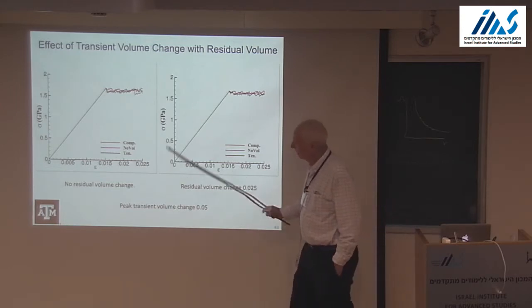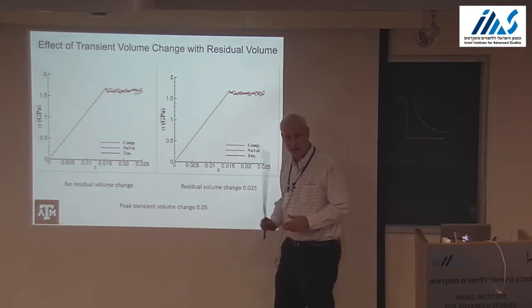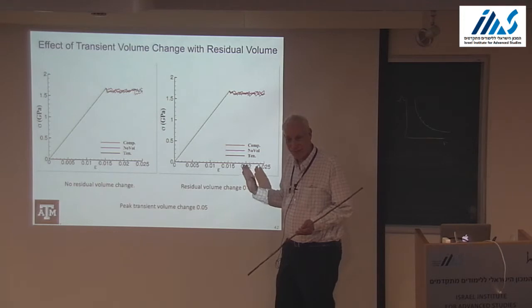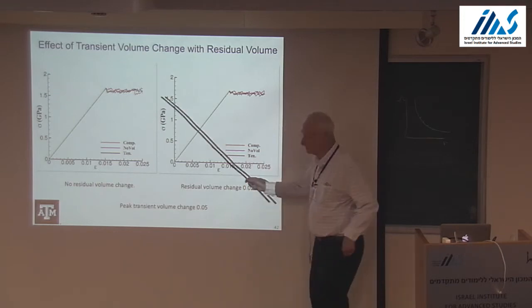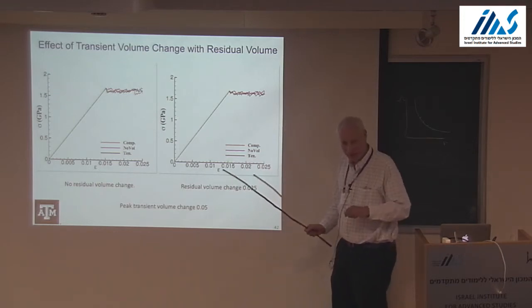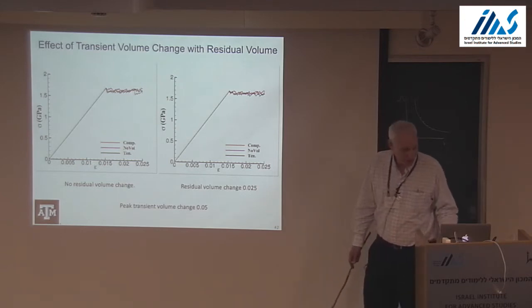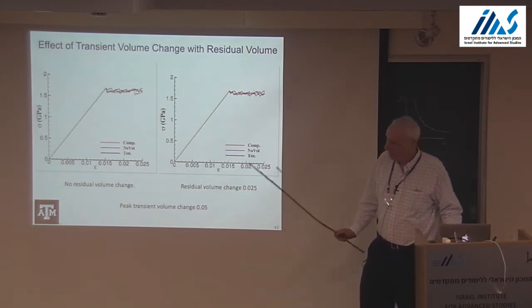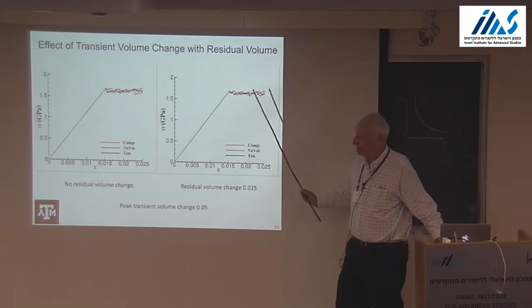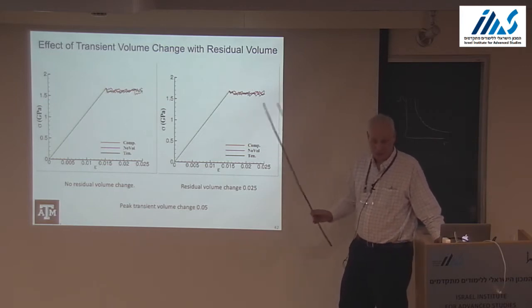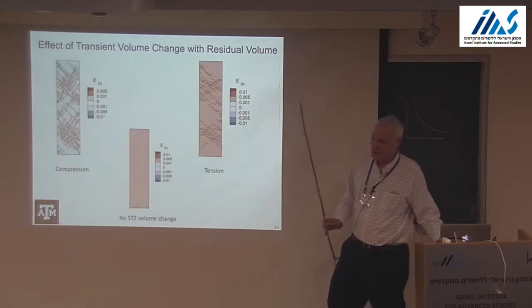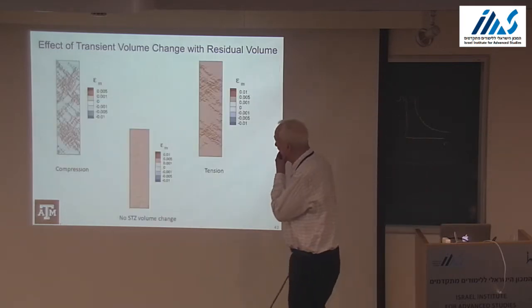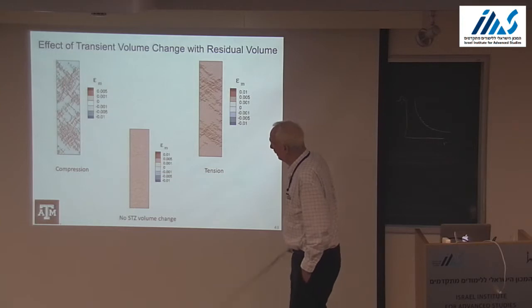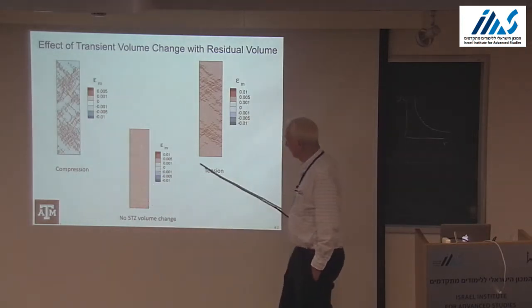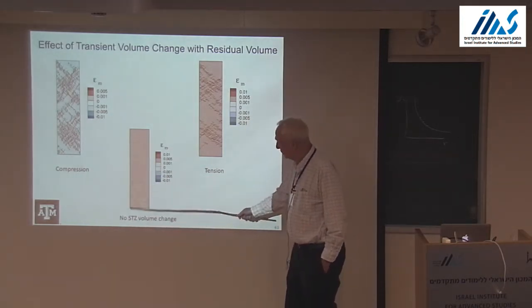What was surprising to us is it makes very little difference in the stress strain curve. Very little difference, whether it's tension or compression. We expected some tension compression asymmetry, doesn't happen. What that suggests is maybe it's the initial stress state more than this volume change that determines the tension-compression asymmetry.